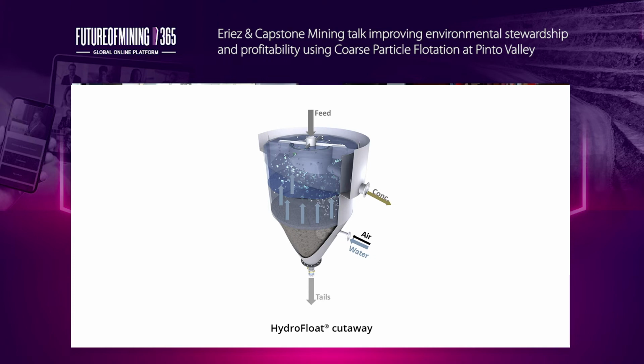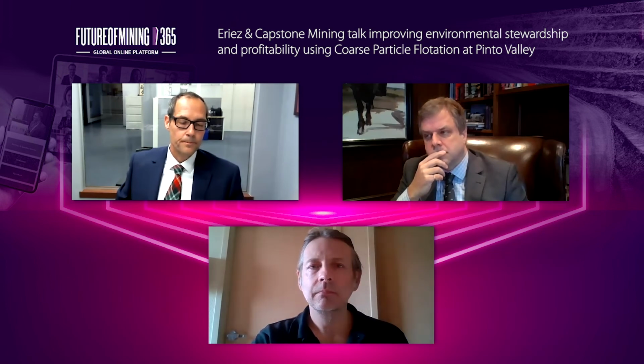Finally, the low shear and the freeboard of the fluidized bed allow the HydroFloat to recover the product by elutriation without the need of a conventional froth layer. And that also improves the recovery of coarse product. All of these innovations combined allow the HydroFloat to recover much coarser ore.